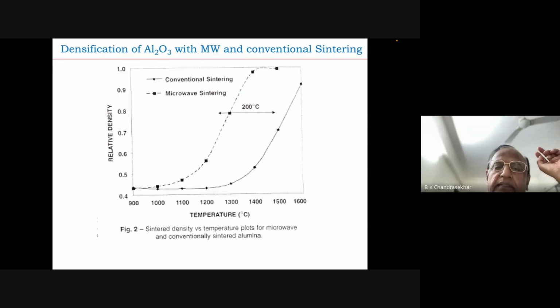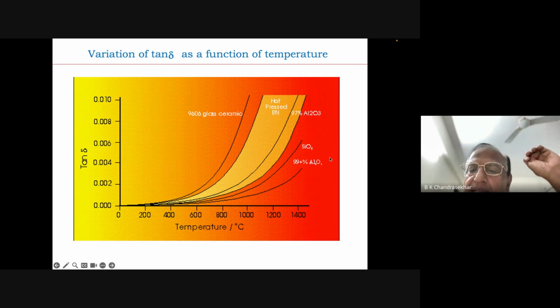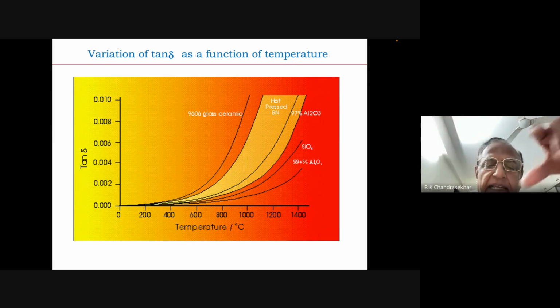This alumina heating by microwave cannot be done by microwave alone, because of the graph I am showing here. Let us look at 99% aluminum oxide. If you see the tan delta, which is basically a representation of epsilon double prime by epsilon prime, it is very low till about 600 degrees centigrade. You see the bottommost line in the graph. Up to 600 degrees centigrade, it hardly absorbs any microwave radiation. Therefore, either you use a hybrid technique, that is use infrared heating or some resistance heating to heat the sample to 600 degrees centigrade and then apply the microwave field, or you apply what is called a susceptor.